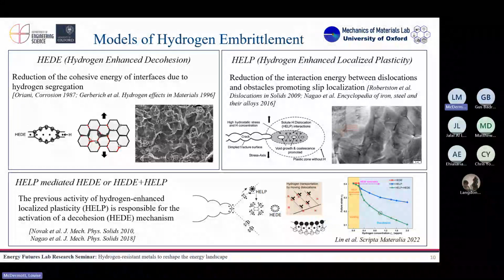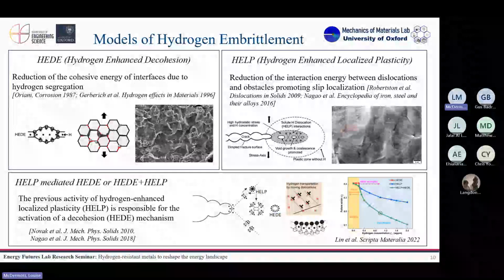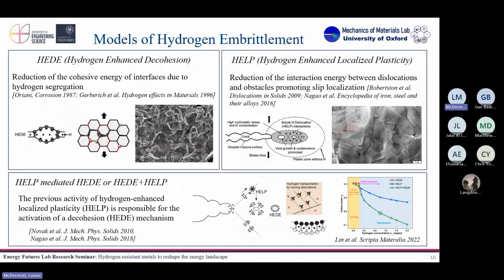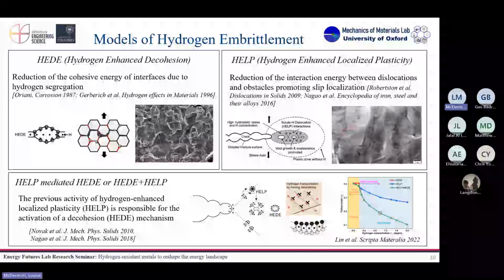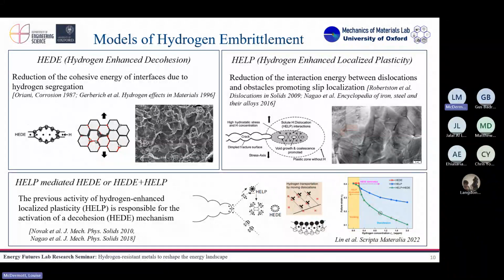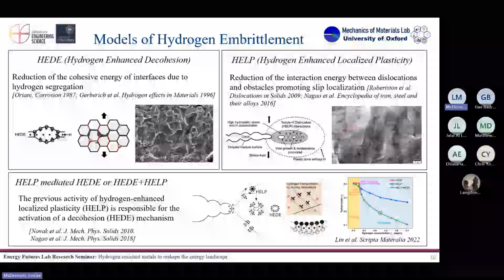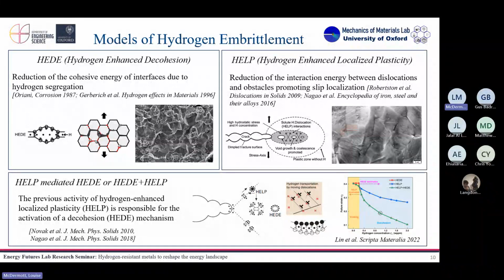There are two that are the most accepted and most important ones, which are HEDE and HELP. I know the names are funny. HEDE means hydrogen enhanced decohesion, and HELP means hydrogen enhanced localized plasticity. This first is the easiest to understand. They say that hydrogen, once it's in your lattice, is able to reduce the interatomic energy between your metallic atoms. So when you pull, and imagine you have hydrogen at your grain boundaries, the energy you need to split those grain boundaries is lower than if you didn't have hydrogen. That's why one of the main manifestations of hydrogen, once you have a broken sample in the lab, is this kind of intergranular fracture. So that's the first theory.